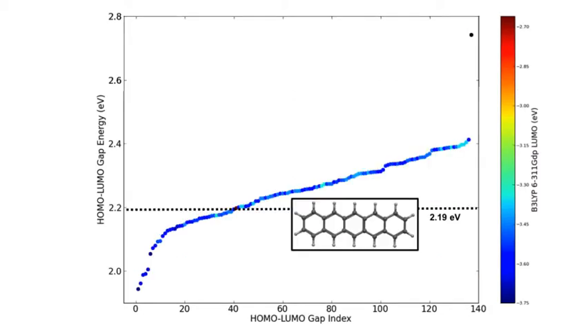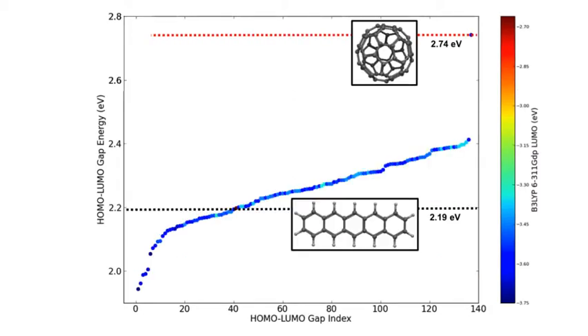Here the HOMO-LUMO gap energies are shown and compared to C60 are predicted to have lower and therefore more favorable gap energies, which should satisfy a partial requirement for enhanced optical absorption.